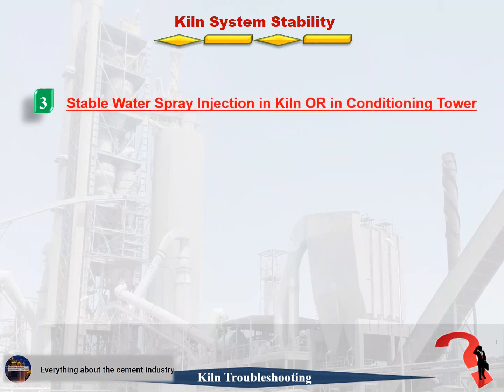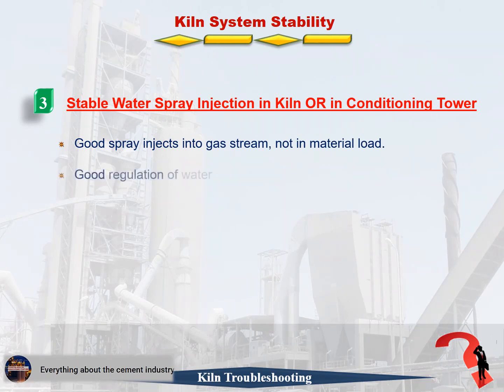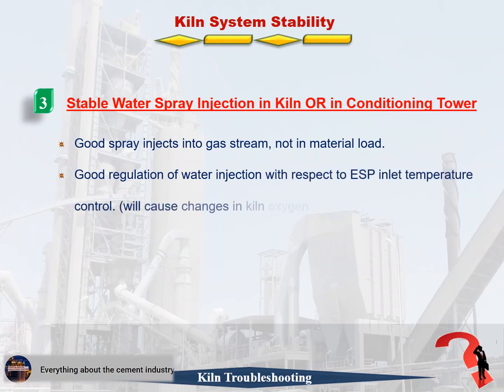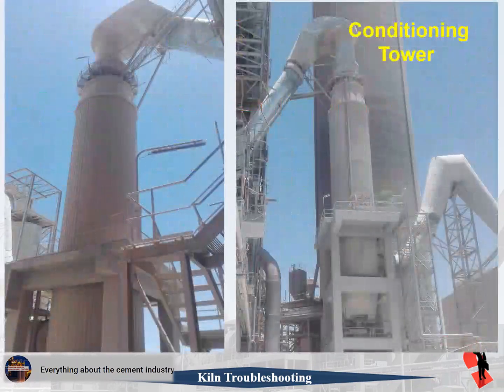3. Stable water spray injection in the kiln or in the conditioning tower. Firstly, good spray injects into the gas stream, not into the material load. Secondly, good regulation of water injection with respect to ESP inlet temperature control; it will cause changes in kiln oxygen level if water flow is not changing smoothly. This picture shows the conditioning tower.